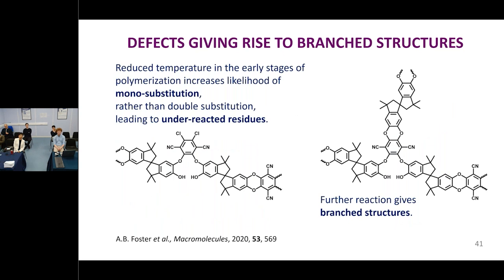But what about branches? In this polymerization, we're trying to be very clever and form two bonds effectively almost simultaneously. Usually this reaction is really, really efficient, like with small molecules, that once you form one of the links which is going to make this ring with two oxygens in, the other one goes quite efficiently. But that doesn't necessarily always happen. Particularly if your temperature is a little bit lower in the early stages of polymerization, when you're starting to build up polymer, you're more likely to get a monosubstituted structure rather than the disubstituted structure that we're looking for. Further reaction then leads to a branch. Now we've got a branched structure.